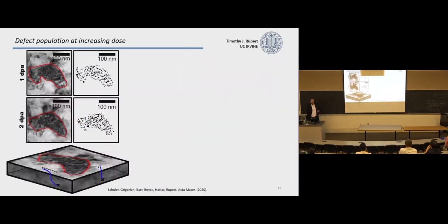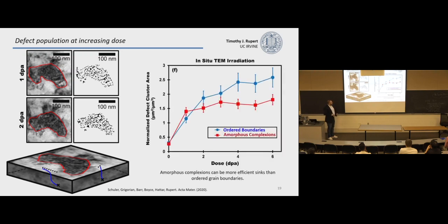More interesting is how that damage builds up inside of the material. So because these are done in situ, we can keep track of where we are in time. This is displacements per atom, a sort of measure of how much you've bombarded your material, and look at individual grains and say, okay, how much defect content do I have in there? And make a plot like this.